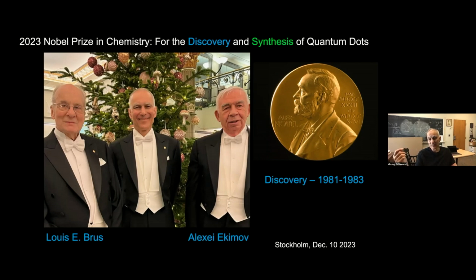In order to get better signal to noise, he thought he should get smaller and smaller particles to increase the surface to volume area. And he found that the particles that he was making, which were nanometer size, as he let them sit on the shelf, the color changed again. And he realized, using an electron microscope, he was able to correlate the color that he was seeing with the size of the particle.